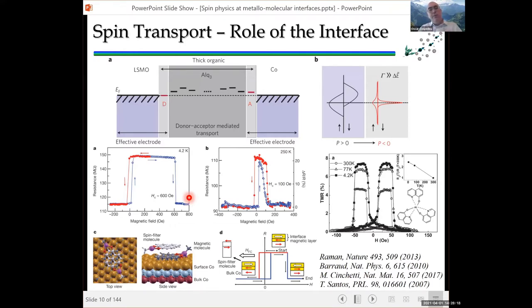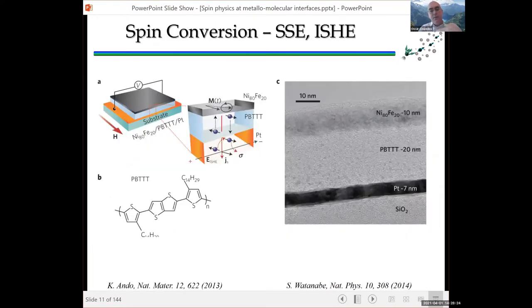Later on, more recently, people are starting to work on how to inject the spins but without applying current. So most typically using pure spin current. So you have ferromagnetic resonance, you excite precession in a ferromagnet, and due to the conservation of angular momentum, you generate a spin current into your non-magnetic material, in this case, PBTTT, in a device that the group from Sirringhaus in Cambridge and Saitoh in Tohoku measured together.